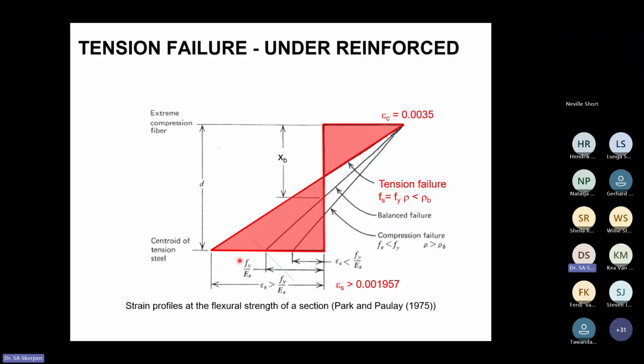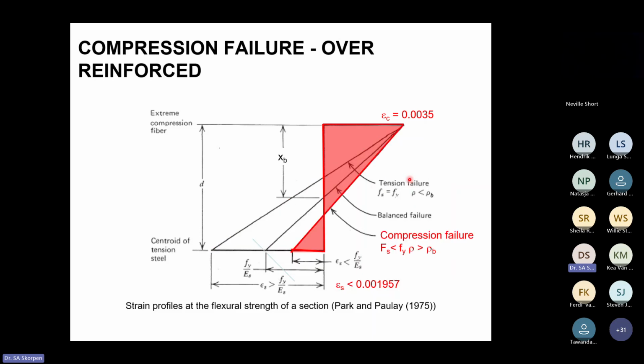what we want to have in our reinforced concrete structures is typically called an under-reinforced beam, where we have a ductile tension failure. And that is basically saying we've got a low enough steel content in the section that the steel yields before the concrete reaches its maximum strain. And we said that maximum strain where concrete would fail brittly in compression is 0.0035. So this is the strain distribution that we want, and this can only be like this if we don't put in too much steel, basically. So we make sure that the steel percentage enables the steel to yield before the concrete crushes, basically. And this would be a tension failure. So we call this an under-reinforced concrete beam, but basically we're forcing the steel to yield before the concrete crushes, which would be a brittle type failure.